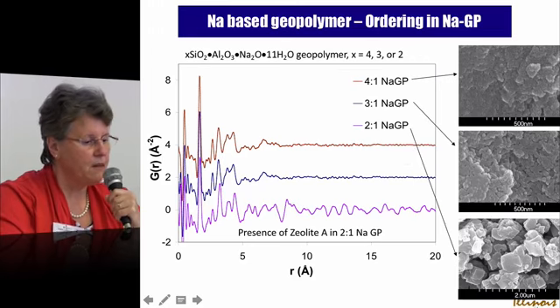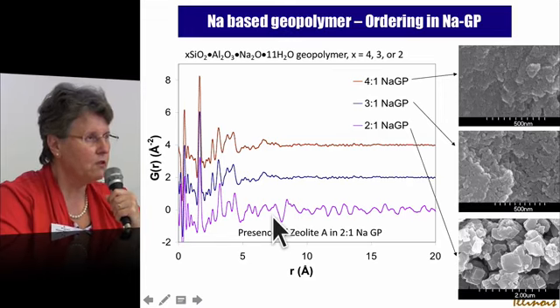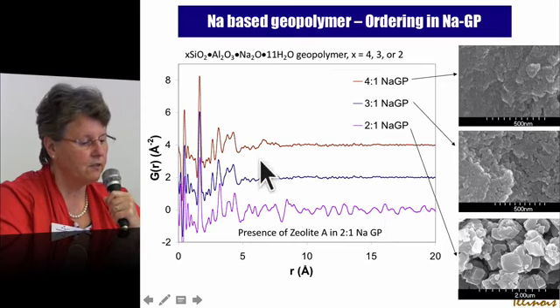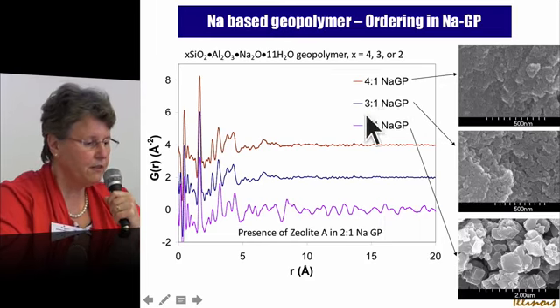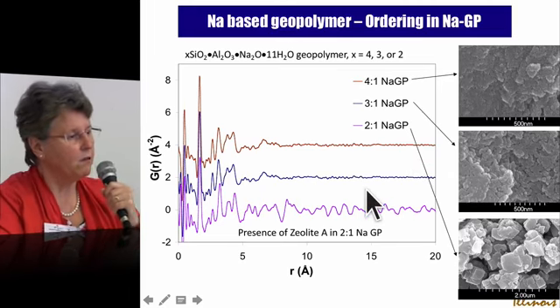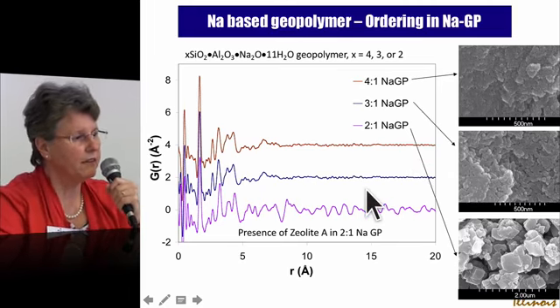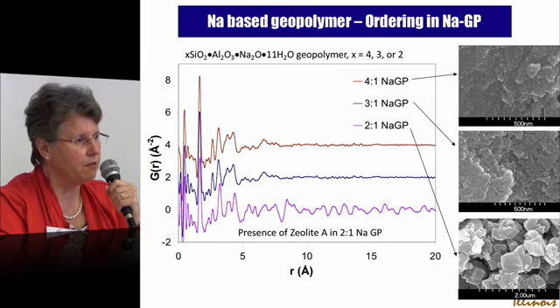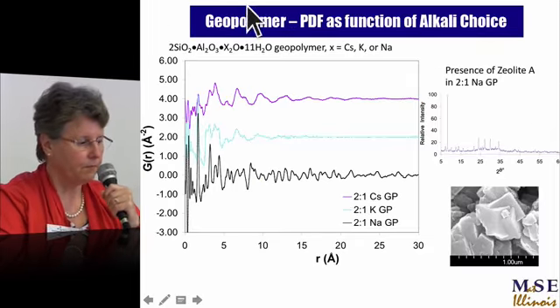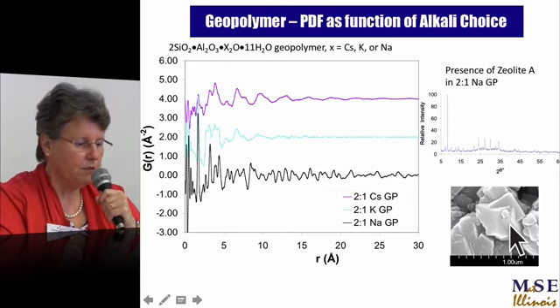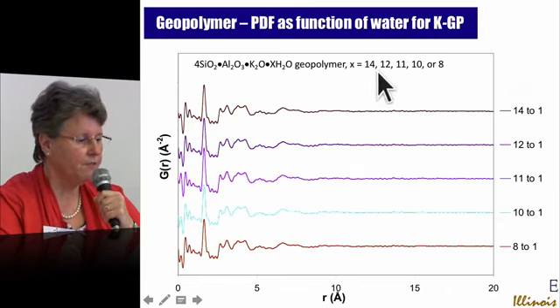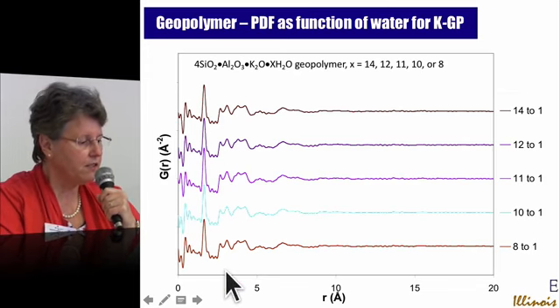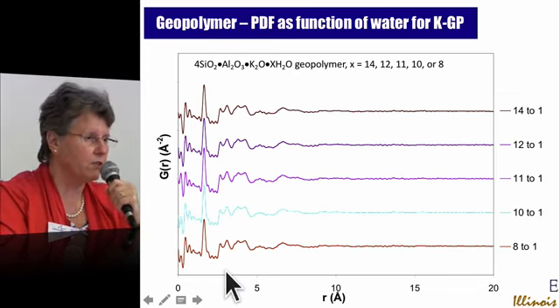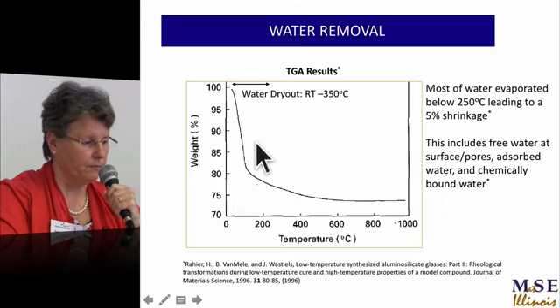Only sodium can make zeolites, that it's 1 soda, 1 alumina, 2 silica. Then you make zeolite, little nanocrystallites, but if it's 3 silica or 4 silica, you don't make zeolites. So only in the case of 1,1,2 composition for sodium can you make zeolites. And so here's a picture of the zeolite. If you add more water, it doesn't change the atomic structure, but it changes the microstructure, makes it more porous.